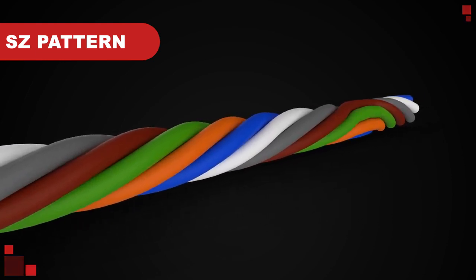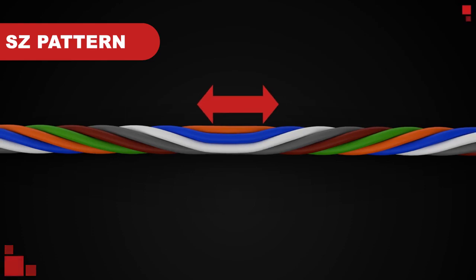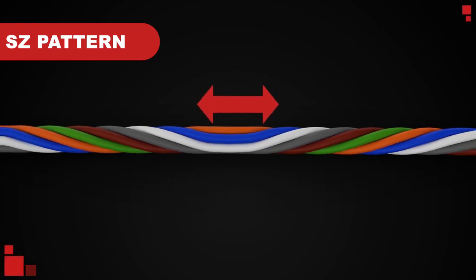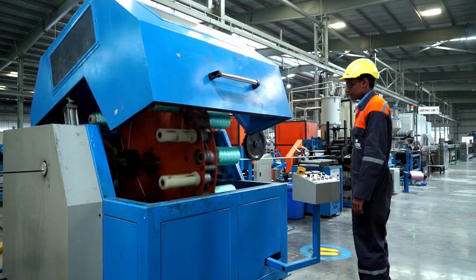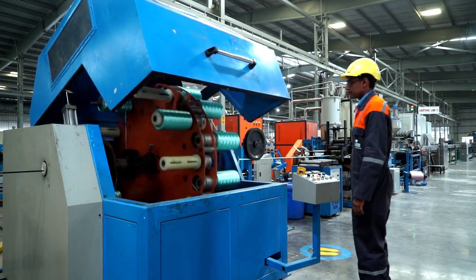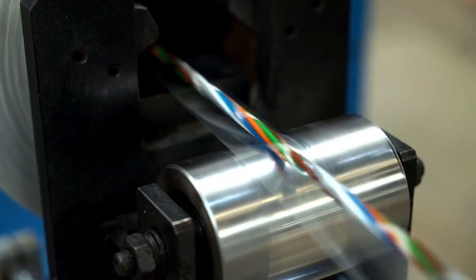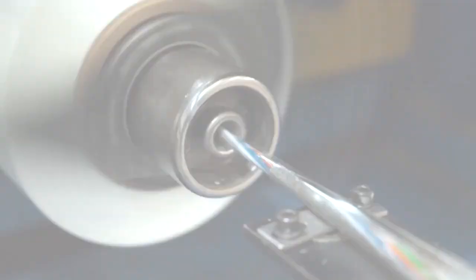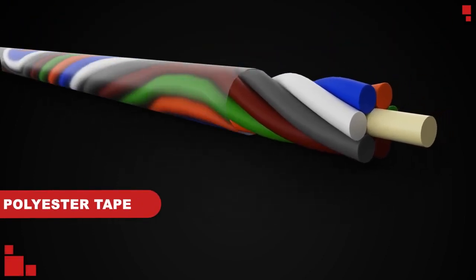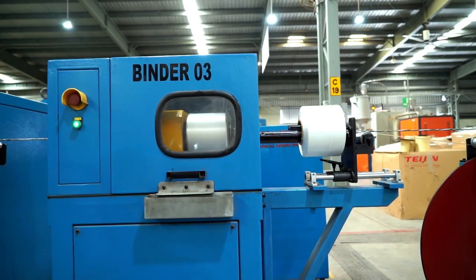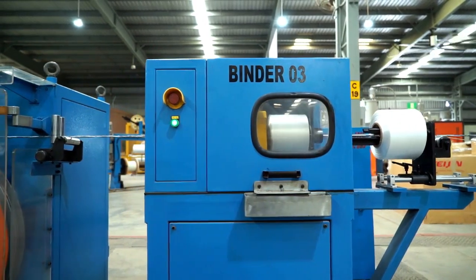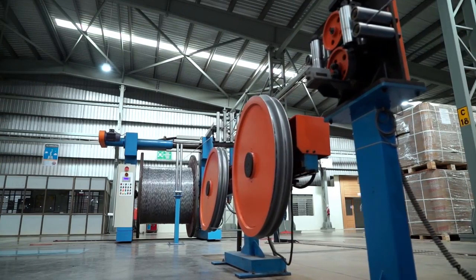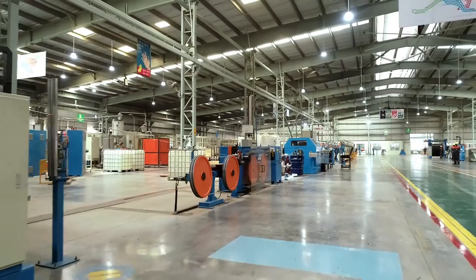While undergoing laying in the field, if the cable gets pulled really hard, the fibers move and adjust using the extra length. In case of a requirement of glass yarn or aramid yarn, the SZ core passes through serve yarn. The strand then passes through flooding jelly and after that, polyester tape is wrapped over the SZ core. Another binder is used to hold the tape at a particular length. Finally, the SZ core gets bound on the spool and now it's ready to go to the next process.